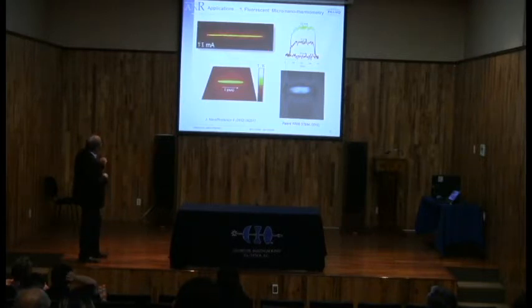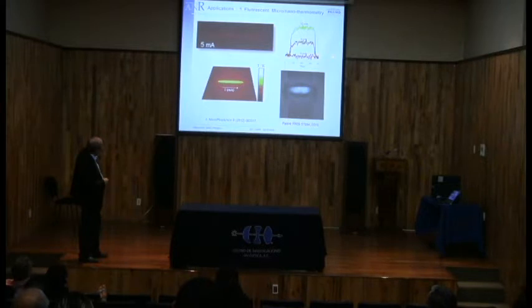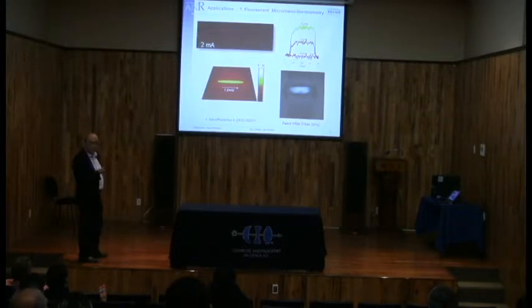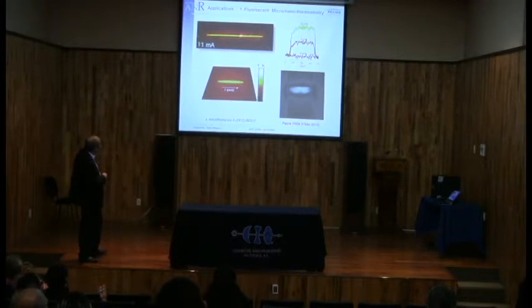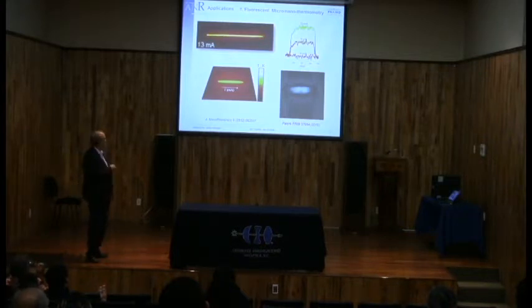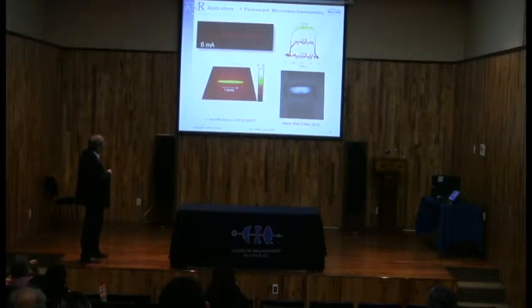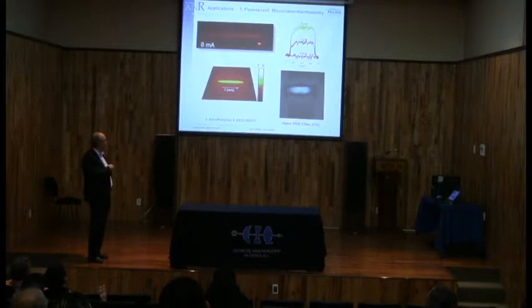Here we have a demonstrator for this. Here we took a conductive wire, where we put current in the wire by this board here. We go from 0 to 15 milliamps. That means that we are heating the wire here to make the switching from low spin to high spin. Because we put the rhodamine in, you see when the system is in the low spin, it's dark, but when it's in the high spin, you see the luminescence here. That means that you can follow the change of temperature as a function of time, as you can see.